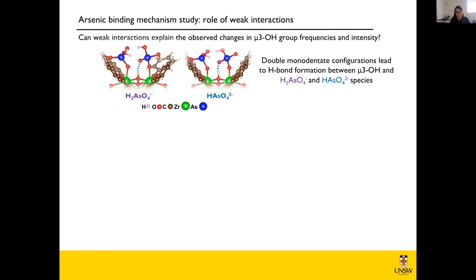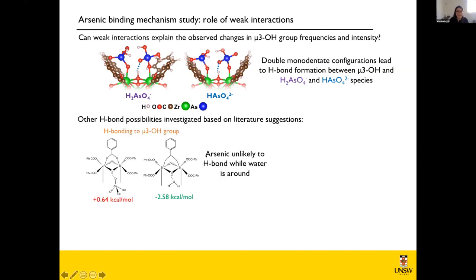In the literature, there were a bunch of other options suggested to explain the mu3OH being affected. One of them was a simple hydrogen bond from an arsenic molecule in solution, but we can see that a hydrogen bond with arsenic relative to a hydrogen bond with water is now less favored. So it's more likely that if there is a hydrogen bond to be formed, it would just be with water. So it would not explain the changes observed with this mu3OH.